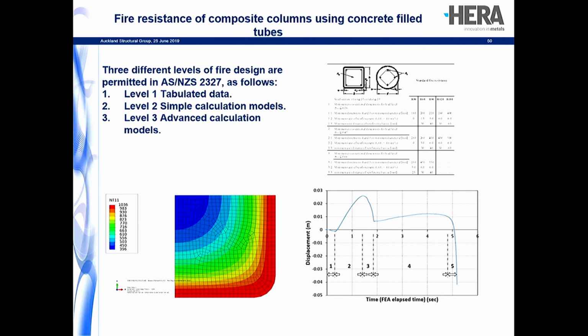When it comes to fire design, there's 3 different options in 2327. There's level 1, which is tabulated data, and an example is shown on the top right-hand side. It's limited, but it gives you safe designs. So this is from, I think, 30 up to 240 minutes fire resistance. The other extreme end is advanced calculation models, and that will be using finite element analysis. This picture on the bottom left is basically showing the isotherms within a quarter of a rectangular hollow section, and it gets hot at the extremity, it gets cooler as you go into the column.